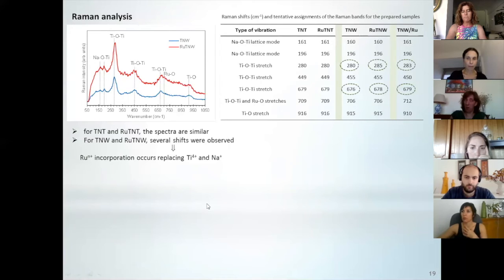What was our next step? Well, remember when I told you that it's possible to prepare titanate nanowire samples with a metal only in the interlayers. So we decided to prepare a sample with the ruthenium only in the interlayers. And then we analyzed the sample by Raman spectroscopy. And in fact, when we have the ruthenium in the interlayers, we can see that we have some shifts. And these shifts can explain why, for the nanowires, we have shifts in this material.